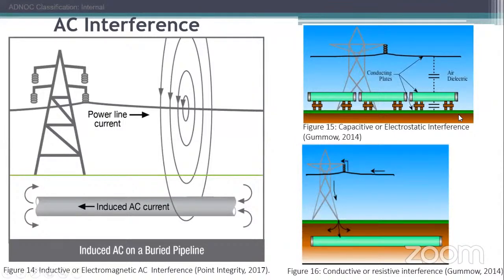So what engineering advises is that if you are doing any work of this nature close to a high voltage transmission line, make sure you do the earthing properly. You ground the pipeline. You understand? If it's a short piece, no problem. But once it's more than 30 meters, according to standard, you try to introduce a grounding system. So that's for capacitive.